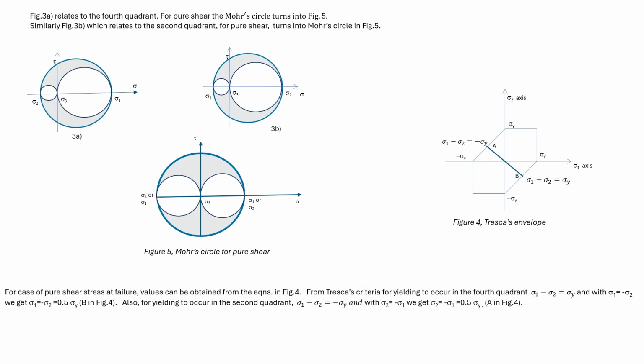Here we look at a particular case, the case of pure shear, and plot the corresponding points on the Tresca envelope. In pure shear, sigma 1 is equal to sigma 2 in magnitude. For Tresca's criteria, this is the equation for the fourth quadrant. So if sigma 1 is 0.5 sigma y, then sigma 2 is minus 0.5 sigma y, which is plotted as point B. For Tresca's criteria, this is the equation for the second quadrant. If sigma 2 is 0.5 sigma y, then sigma 1 is minus 0.5 sigma y, which is plotted as point A.